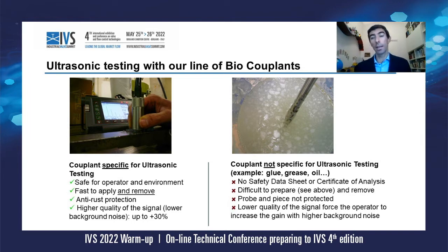If you use, on the right in the picture here, a non-specific couplant for ultrasonic, typically glue or grease or oil, you will get no safety data sheet or certificate of analysis showing sulfur and halogen levels. They are difficult to prepare, as you can see. They form a lot of clots. It takes time to be ready. And also it's difficult to remove because glue is made to stick, not to be easily removed after the testing. The probe and the piece are not protected, of course, from rust, and you have a much lower quality of the signal. So you need to increase the gain with higher background noise.